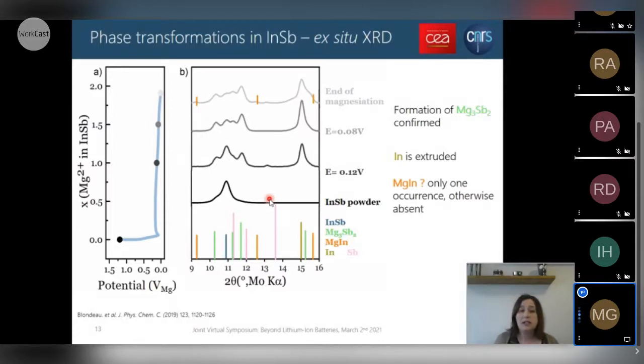So as we've seen, the capacity that we obtain, the electrochemical behavior, cannot be explained by the sole reactivity of Mg3Sb2. So this MgIn phase has to be here, and it's here in an amorphous state, which means that we have an electrochemically driven amorphization of MgIn in the first magnesiation.